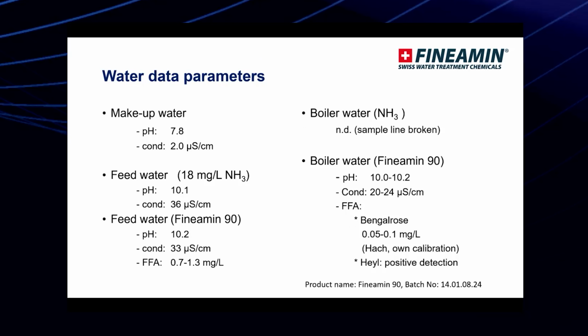So the water data parameters: the makeup water is pH 7.8, conductivity around 2 microsiemens per centimeter. Feed water using ammonia, the pH will be around 10.1, conductivity 36 microsiemens per centimeter. This is using the ammonia. When you use Fineamin 90, we try to make the pH as close as possible, around 10.2, conductivity 33 microsiemens per centimeter. We did measure the FFA, the active FFA, around 0.7 to 1.3 ppm.